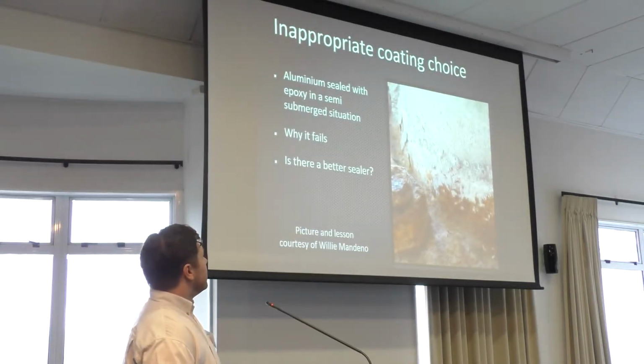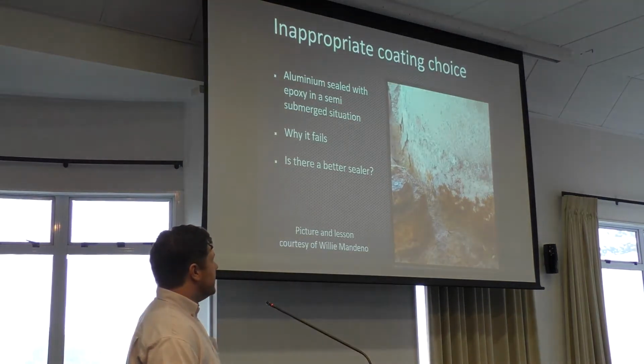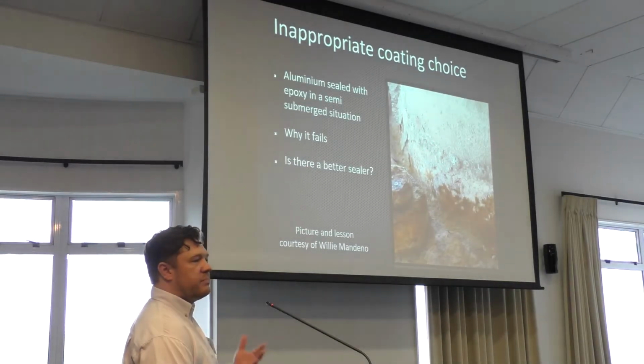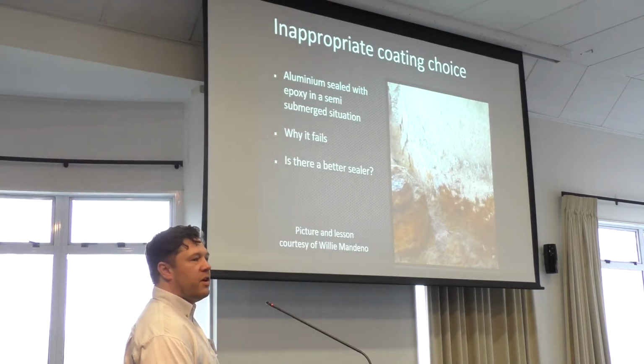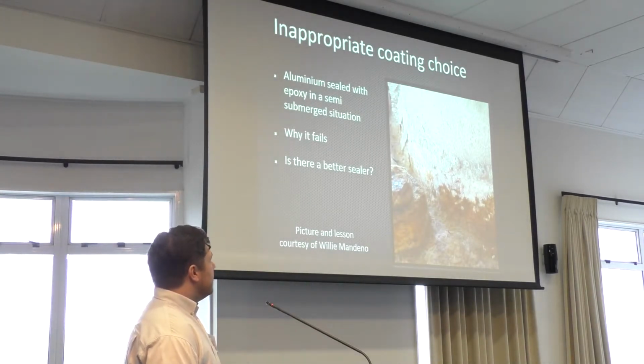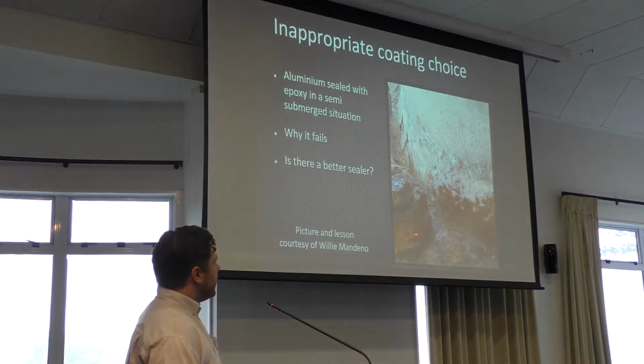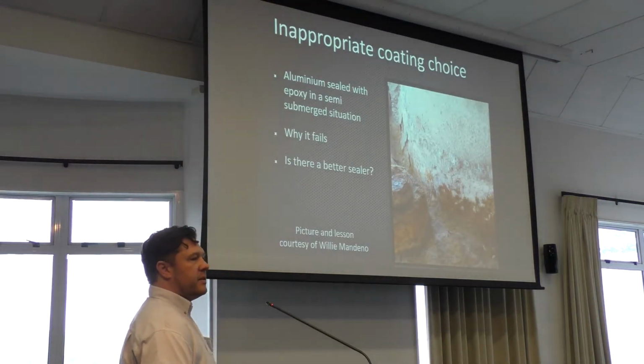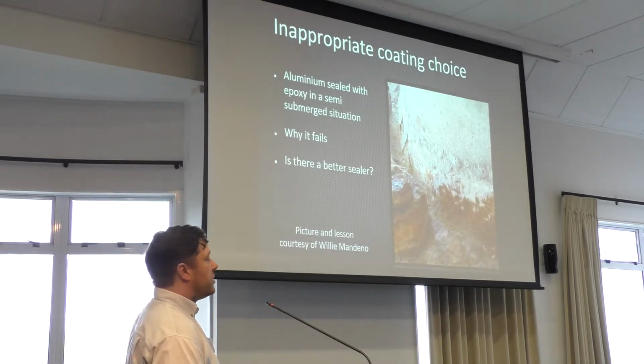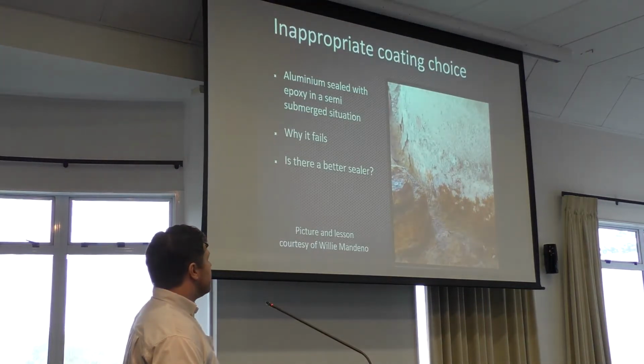So they put an epoxy sealer onto an aluminium coating, and you can see here bubbles fizzing up where the aluminium underneath the epoxy has been activated, and you don't get much of a worse corrosion environment than that. You can see the coating's kind of intact up here, but around here it's just all been spent because the coating that's been exposed is corroding, trying to protect an area larger than what the coating is covering. It's an anode. So the failures happen pretty quick like that. Now I believe they use aluminium without sealer in those situations and they don't suffer the same troubles.